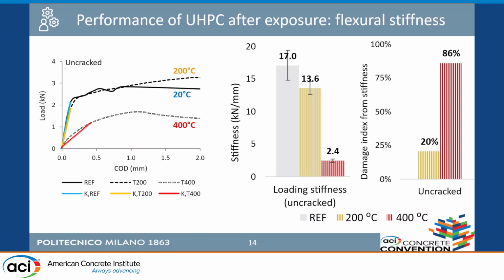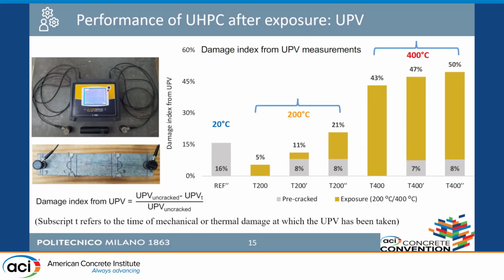We performed a similar study also for the stiffness, but I prefer to move to the summing up, that is some slides later. This is what we get with the ultrasonic pulse velocity measurement. So we can see here that we split the effect of the pre-cracking. Just for pre-cracking, we are damaging concrete, so we have a decrease of the pulse velocity of 16%, while if we heat an uncracked specimen, we have a loss of 5%.